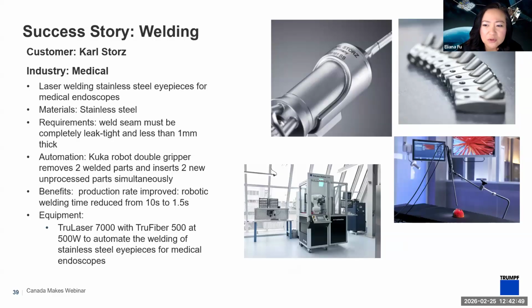This one is a customer called Karl Storz. So basically, this is welding eyepieces for medical endoscopes. And Karl Storz is a German customer, but they're also used in many other applications, including robotic surgery these days. So these just happen to be stainless steel, and then the weld seam has to be completely leak tight, with less than 1 millimeter thickness. Attach that to a robot that also removes the welded parts and then inserts two parts so you can have it semi-automated. And using the robotic welding reduces the time from 10 seconds to 1.5 seconds. So 1.5 seconds to make a weld. So really you can improve that process a lot and speed up your production.